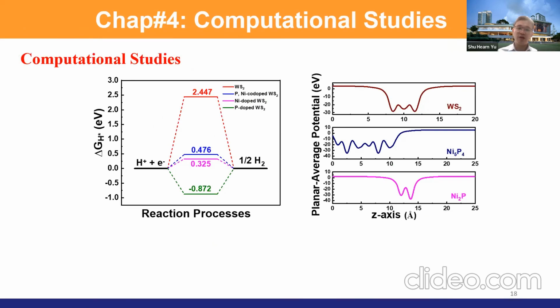So we try to do some computational study, and we find that this one is the nickel doped tungsten disulfide, and this one is phosphorus and nickel co-doped tungsten disulfide. However, the formation energy of this is very large. It's a positive value. We don't believe that nickel is successfully doped into WS2. So these two results are not very useful for us. We just do a case study.